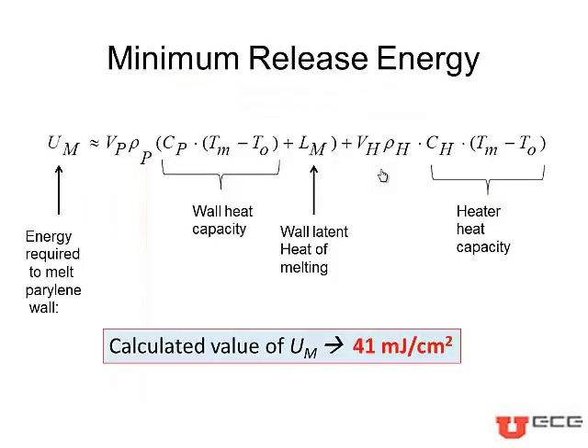We can actually calculate the amount of energy required to melt the parylene wall. There are two components to the energy needed. First is the heat capacity of the polymer wall and the heater from room temperature to the melting temperature of parylene, which is about 290 degrees Celsius. And the second component is the latent heat of melting of parylene. We calculated the exact amount of energy considering the dimensions of the reservoir, which turned out to be 41 millijoule per centimeter square.